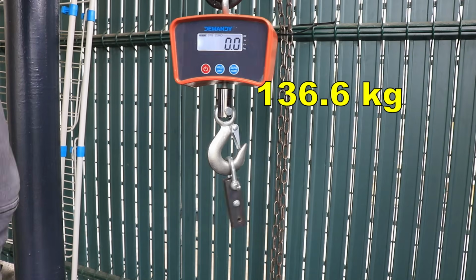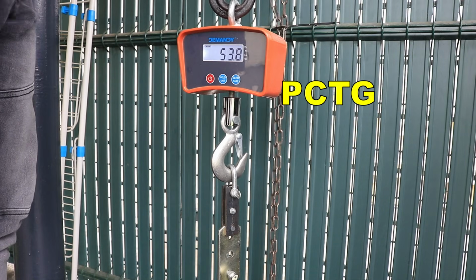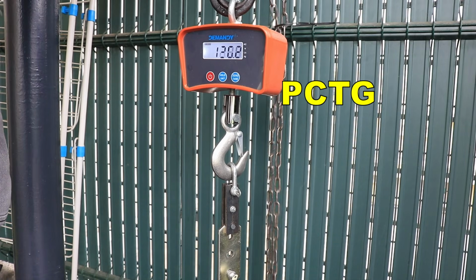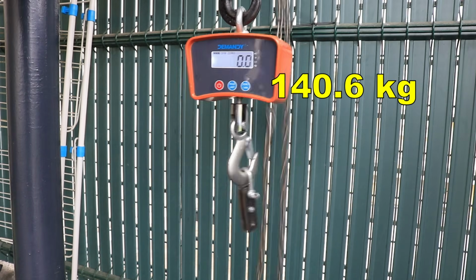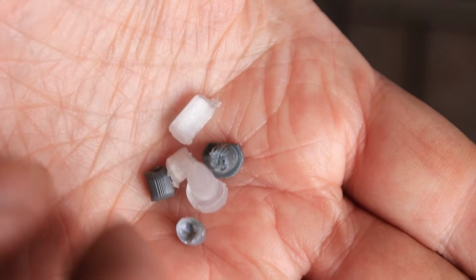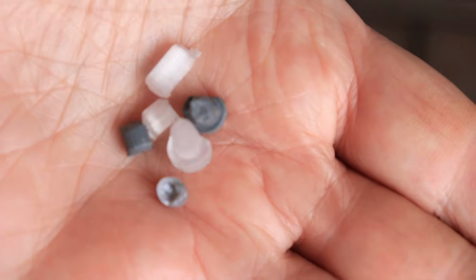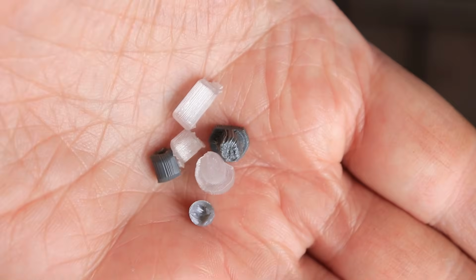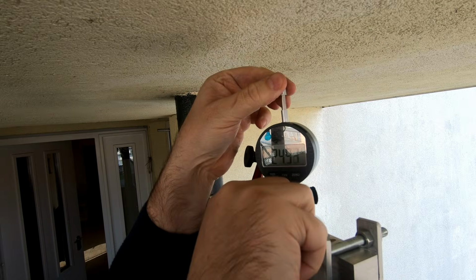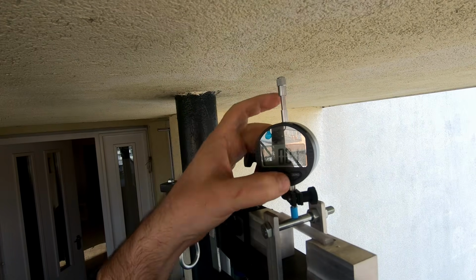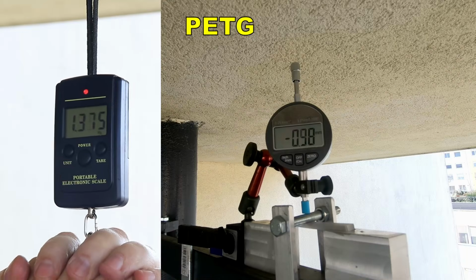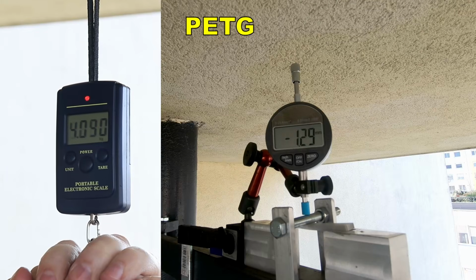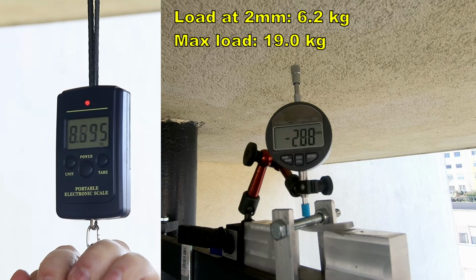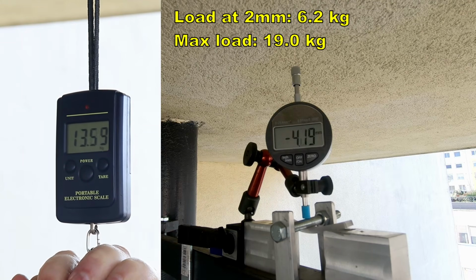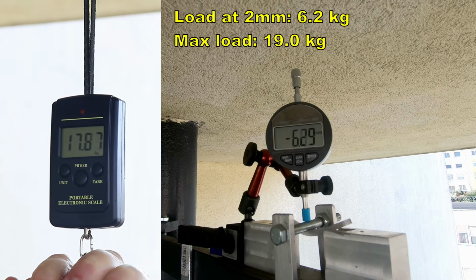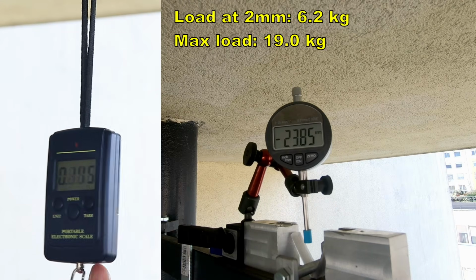Starting with PETG. This is PCTG. And they all broke on those cross-section areas where they should for the shearing. The next is the bending test, 3-point bending test. I'm starting with PETG. Distance between supports is 50 millimeters. And I want to record the load at 2 millimeter deformation and the maximal load.